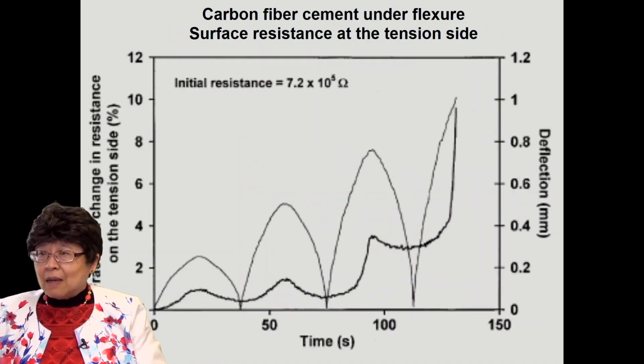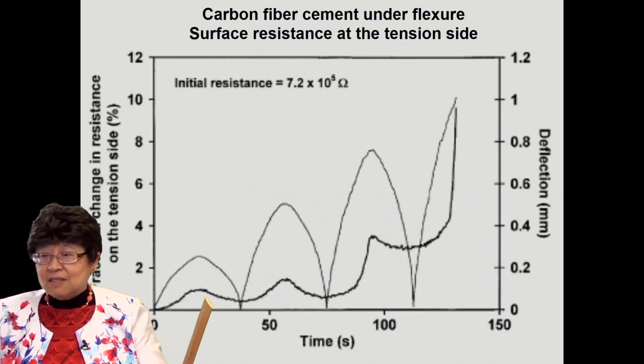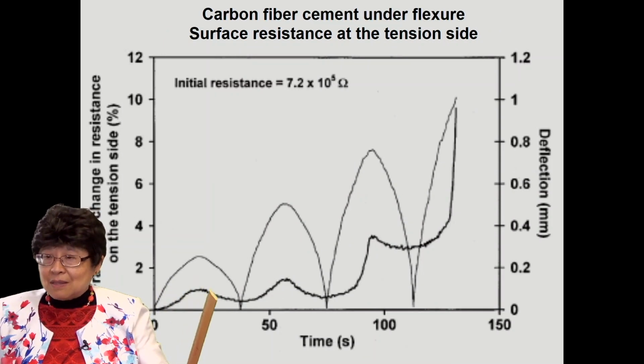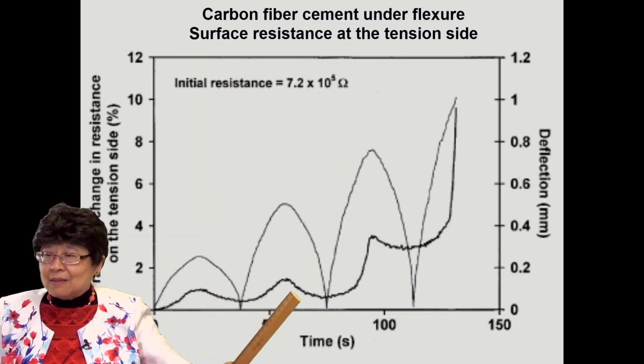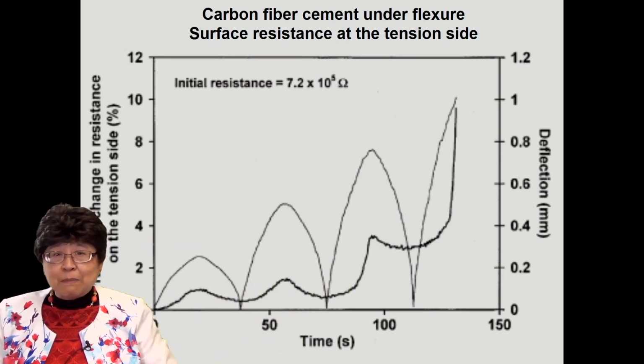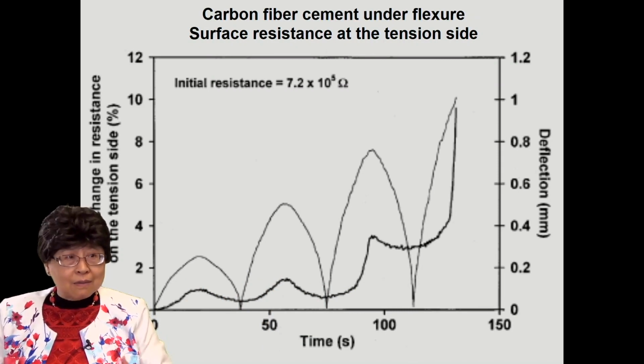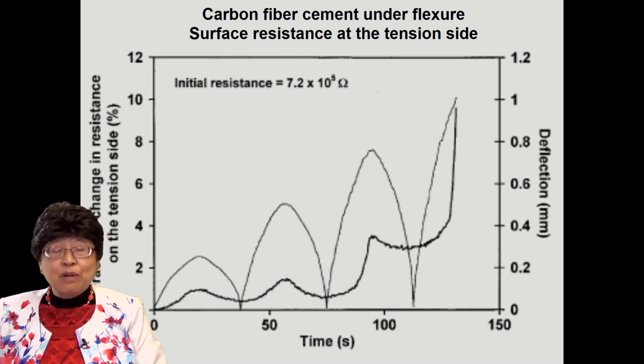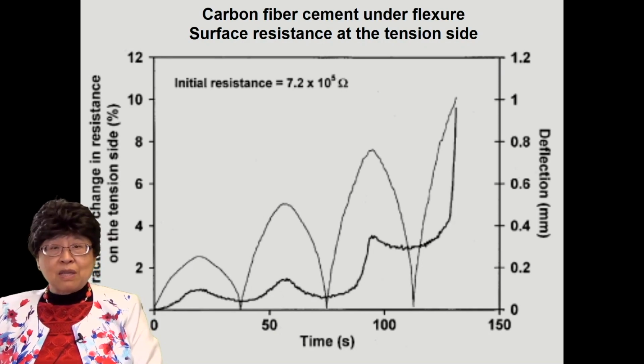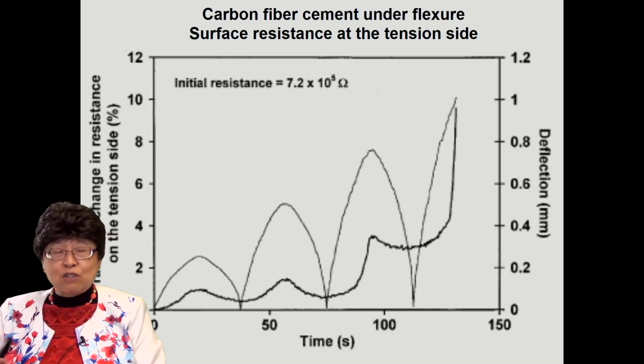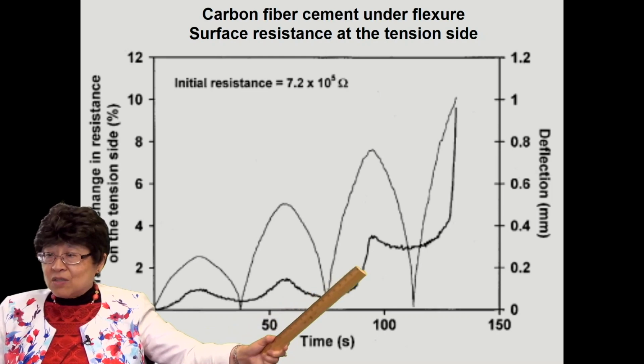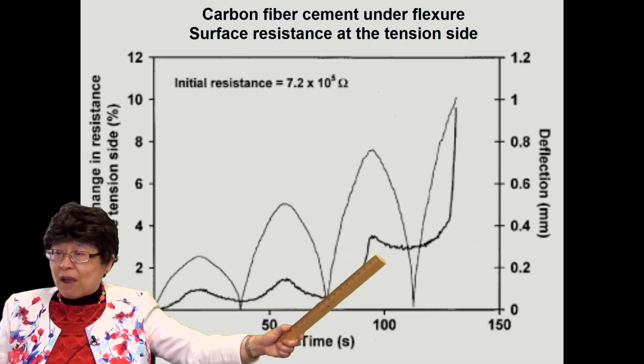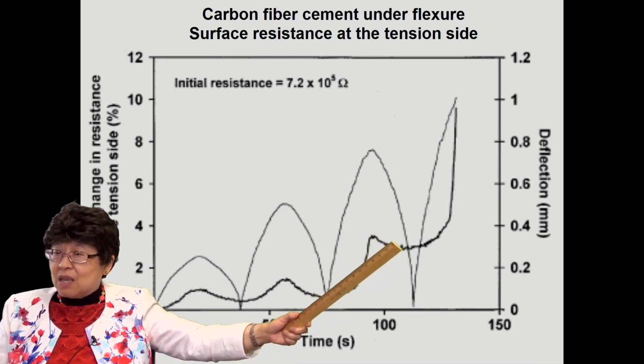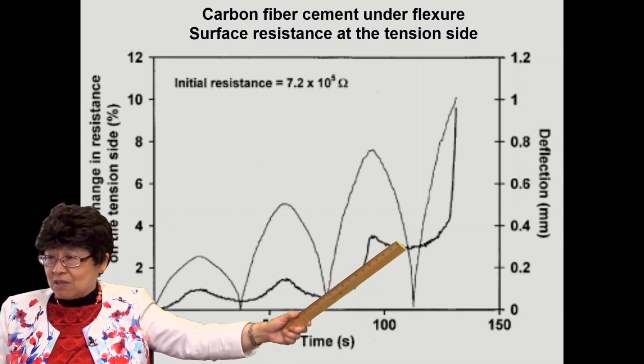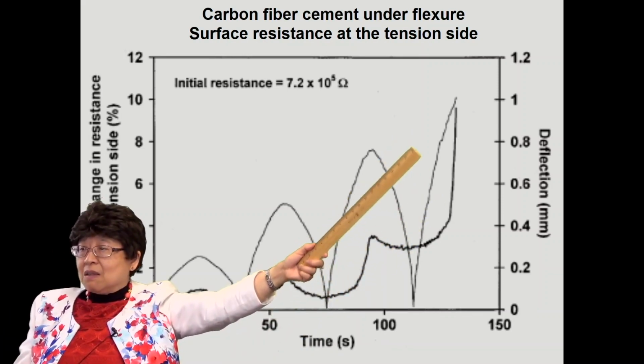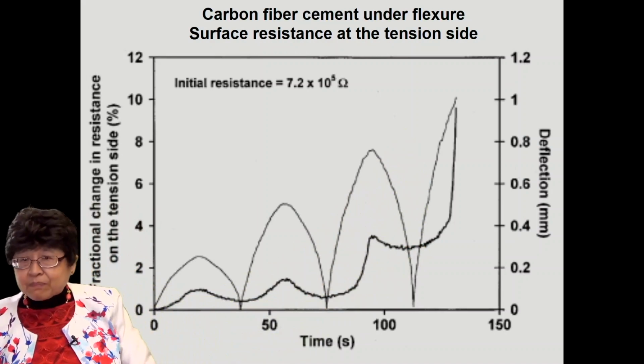On the tension side, it just does the opposite. The resistance increases. Okay? And on the tension side, it's particularly prone to damage. Cement is a brittle material. Brittle materials in general are very prone to damage under tension. And you can see that this damage gives rise to an irreversible increase in the resistance on the tension side. And obviously, when it breaks, the resistance shoots up.